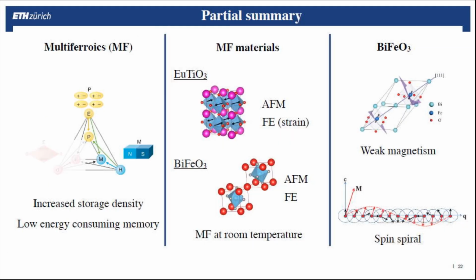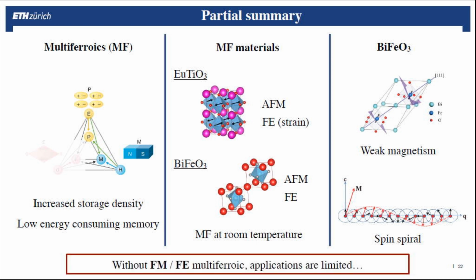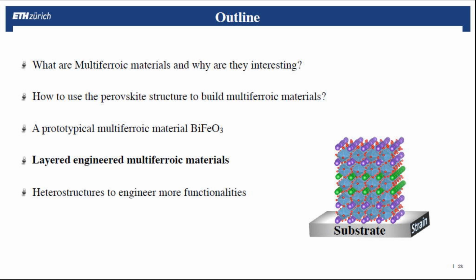So just a partial summary. I told you that there are multiferroic materials that combine these different properties. They're interesting because one can have an increased storage density or a lower energy consumption memory. I told you that there are two prototype examples. Europium titanate, which is antiferromagnetic and ferroelectric when one applies strain. I told you that there is also bismuth ferrite, which is antiferromagnetic and ferroelectric, and multiferroic at room temperature. And what I told you is that actually bismuth ferrite is antiferromagnetic with a weak magnetism, but this is not enough to have a net magnetization. So still, this is not a ferromagnetic ferroelectric system. And without being ferromagnetic and ferroelectric, it's difficult to sell this material for applications. So let me show you now another way to engineer multiferroic materials.